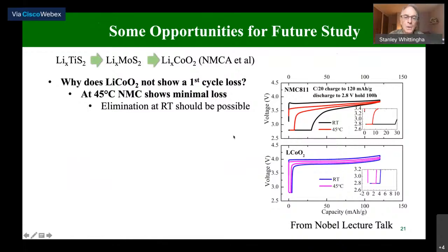So what is the situation with cobalt oxide? Let me show you again, 811. The black curve here is the curve at room temperature, and this is charged to about 120 milliampere hours per gram. If you now do this at 45 degrees centigrade, it's the red, and you can see it's much better. And if we hold it at 2.8 volts, we get almost all of it back. So that's similar to what I showed you before.